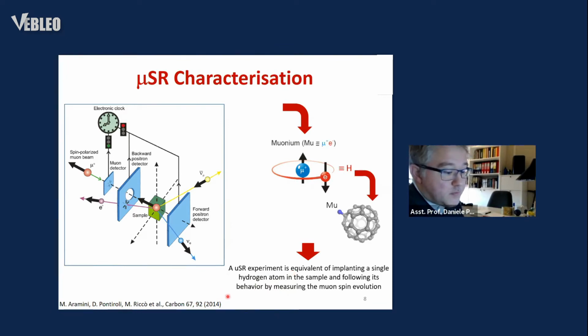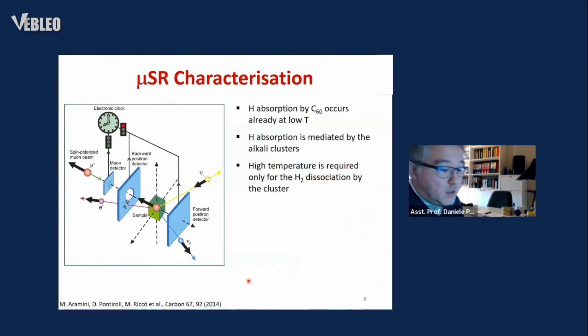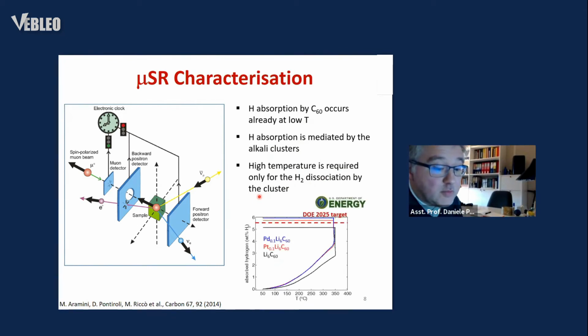In the presence of hydrogen molecules, in our case, mu-SR allows us to understand that atomic hydrogen absorption already occurs at very low temperature in the fullerene molecules. And in the presence of hydrogen molecules, the dissociation process is mediated by the alkali clusters, whose limiting factor is represented by the still relatively high dissociation temperature. This process can be, for example, catalyzed by adding small amounts of platinum or palladium nanoparticles.